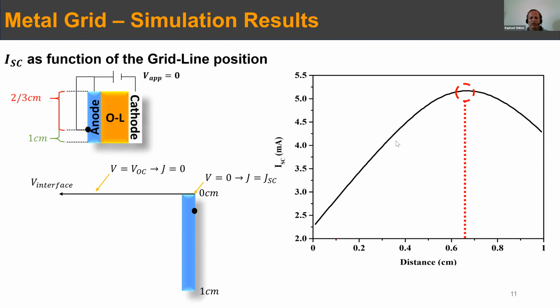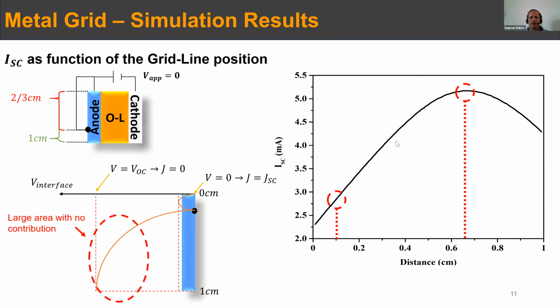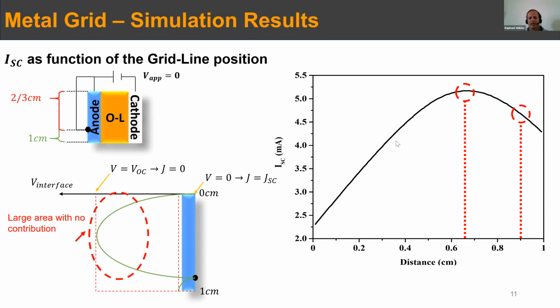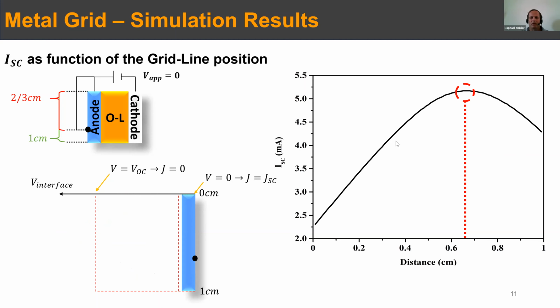And just to give you the intuition, the idea is that if the grid line point is very, very close to the main collection point, then you have a large area with no contribution to it. If you go to the other extreme, then the area from this point to the major collection also will be a large area with minimal contribution, and therefore the best way is to position it at 2/3, so that you will have equal distribution of maximum voltage between these 3 cells. We didn't manage to prove that mathematically, but at least experimentally it works.